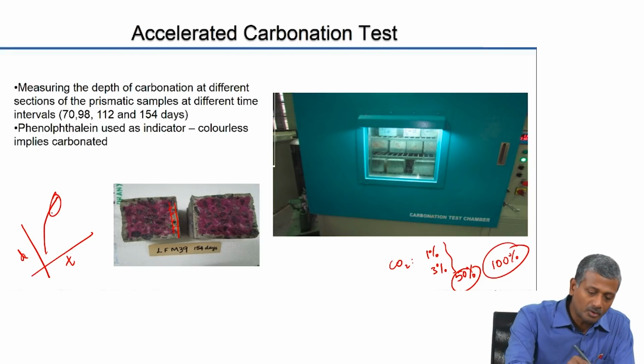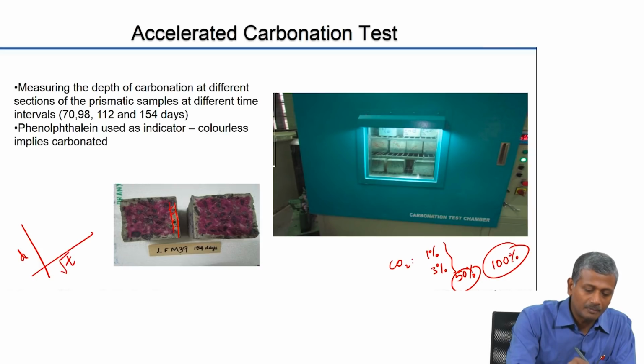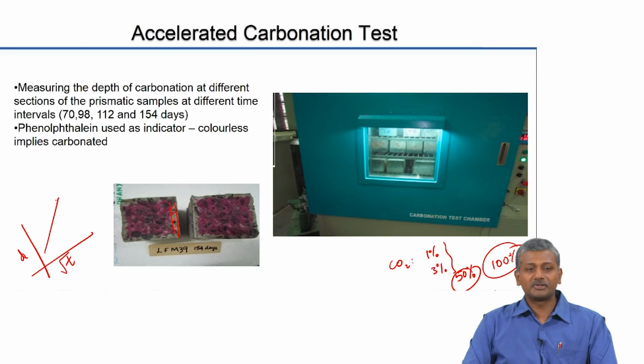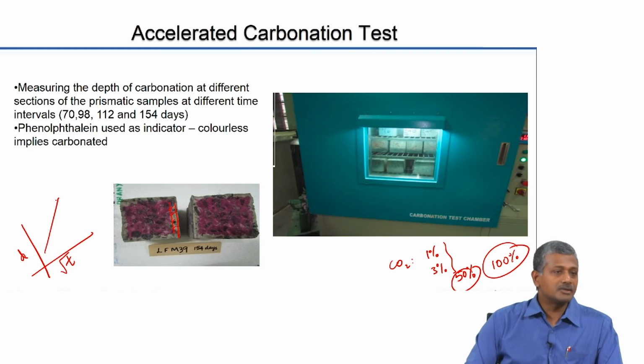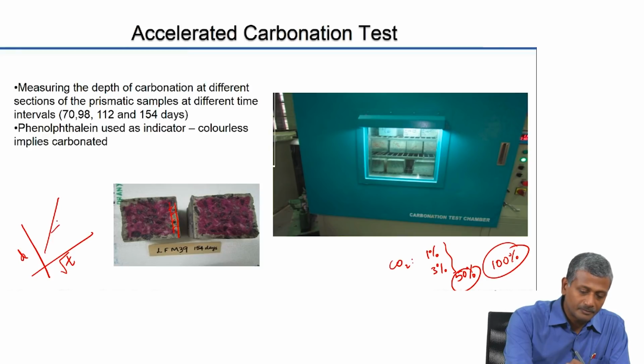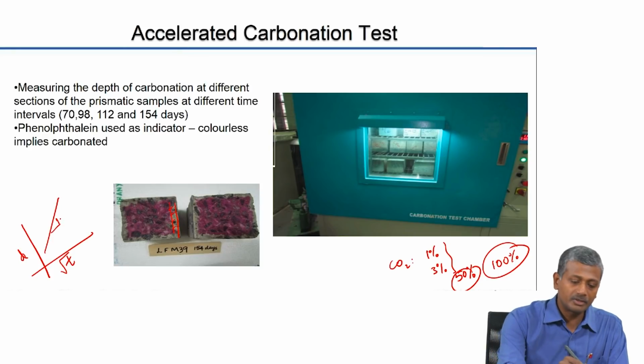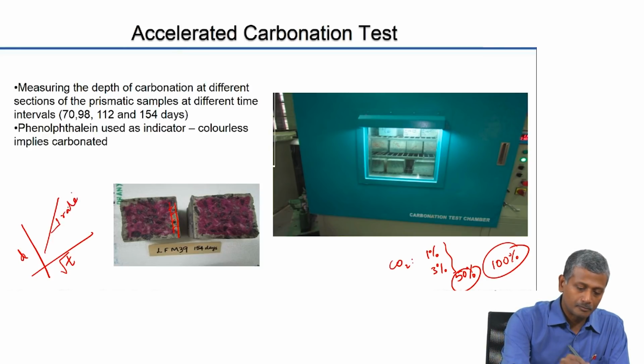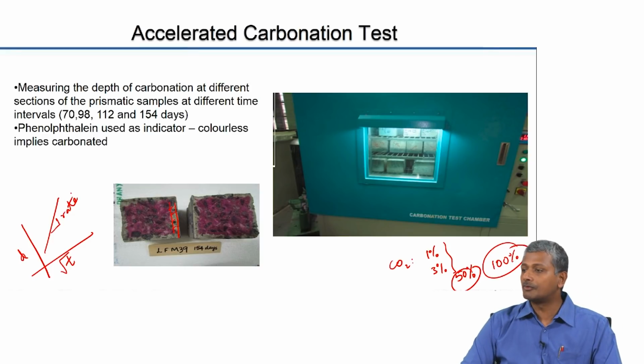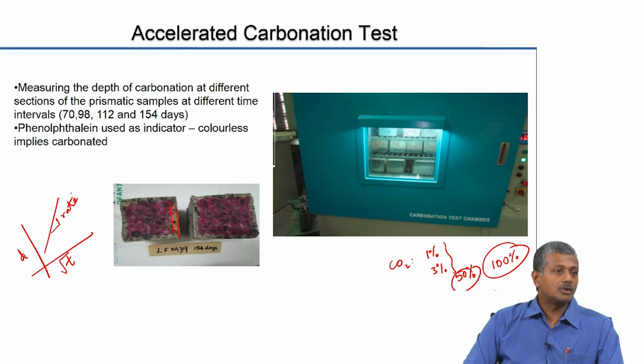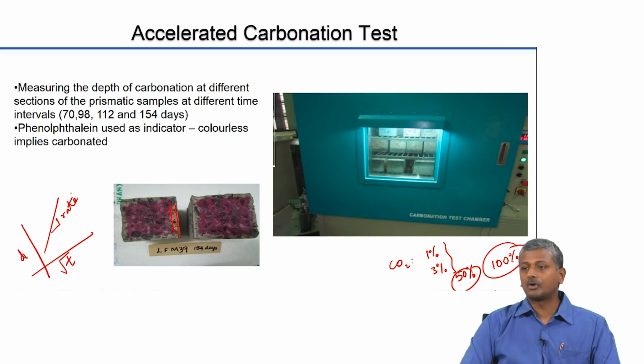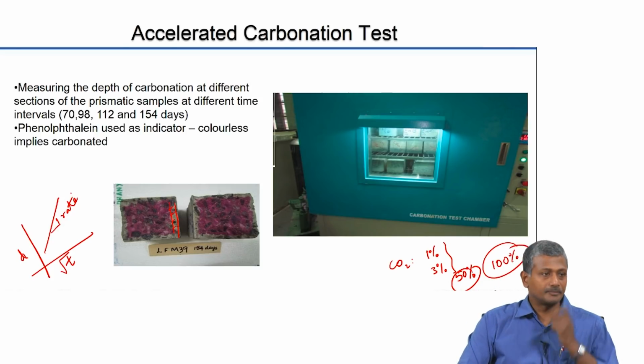So, that is why when you plot it against the square root of time, you get a linear relationship. And the advantage here is, you can actually then take the slope of this and call it the carbonation rate. And that carbonation rate can further be used for modeling the concrete or understanding the service life of concrete exposed to a carbonation environment.